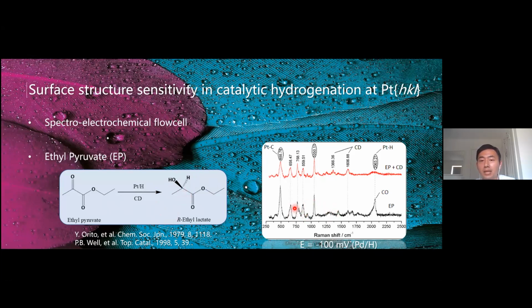With the setup, this experiment was repeated, and we could see from the black spectrum a peak just below 500, which is the platinum-carbon bond. The 1050 wave number is due to the platinum carbon-oxygen, carbon-OH bond close to the surface. We could also see that some amount of CO was formed due to the high reactivity of platinum.